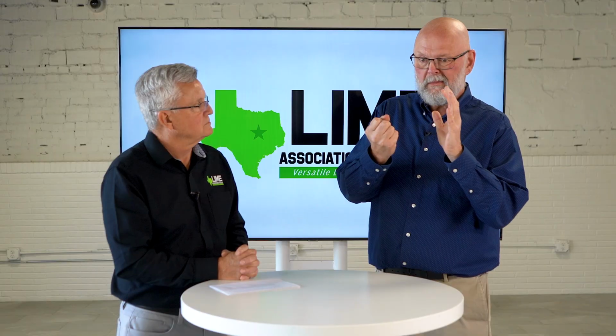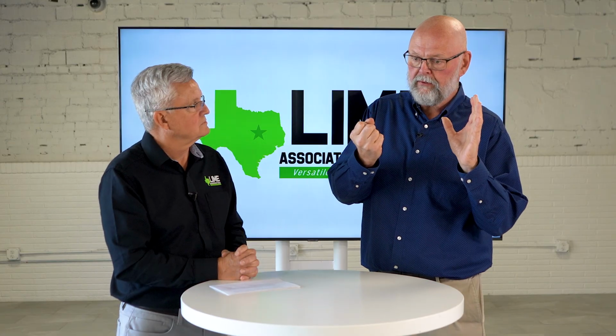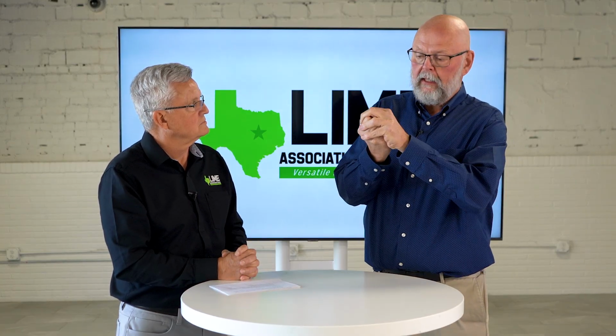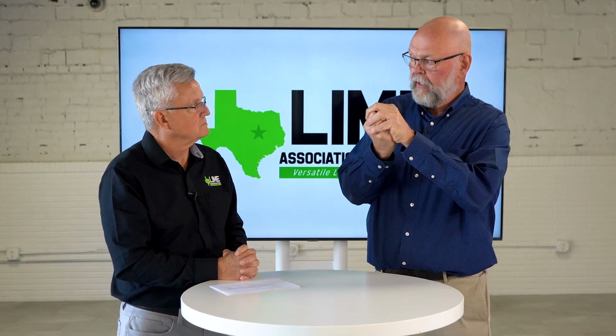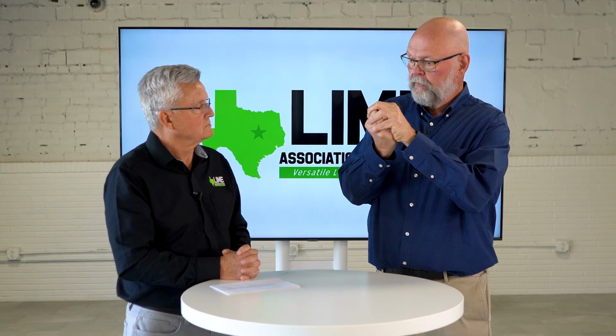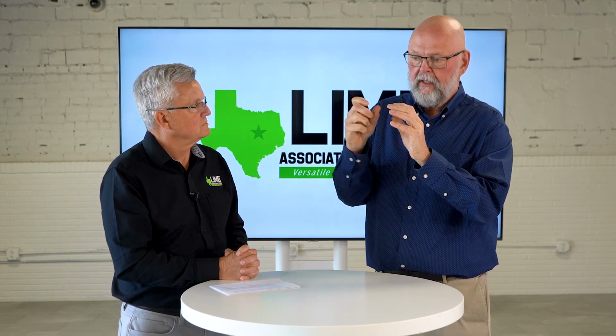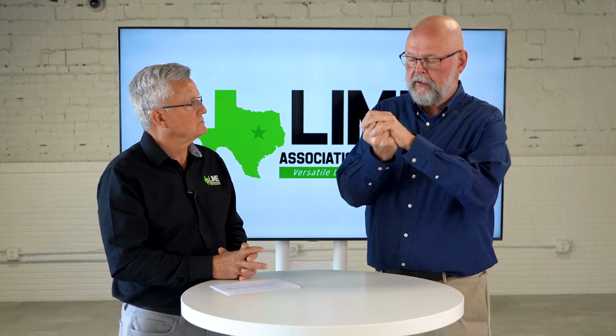Well, and that's the other thing. If you think about it on cement, everyone's worked with it. It sets up very fast. I've got this clay, and there's no calcium to penetrate in. I was talking earlier about calcium getting in the water and going to the clay surfaces. There's none really to get in there. So what does the cement do if you put it in clay? It's going to put an M&M coating on the outside of that clay particle. So we have 50, 100 pieces of little clay cards there, and each is surrounded. You get good strength immediately.